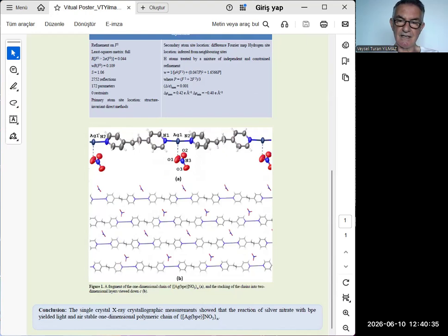This semi-coordination explains the deviation of the N-Ag-N bond angle from the ideal linear angle of 180 degrees. In this case, the coordination geometry around silver may be considered as T-shaped. As shown in Figure 1b, the individual chains are connected by electrostatic contacts into two-dimensional layers running in the ab plane.